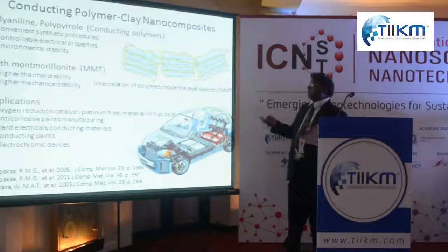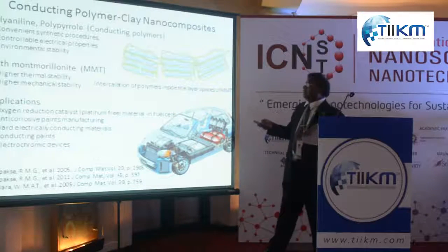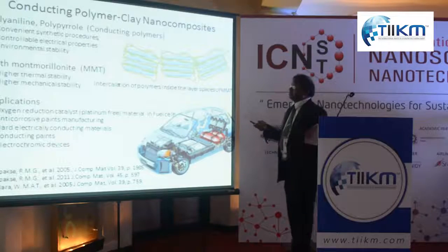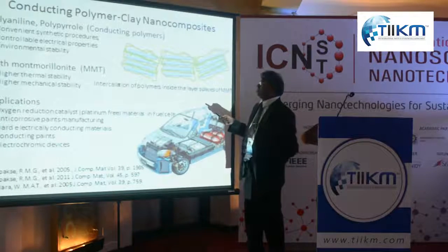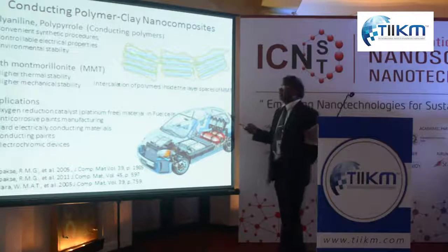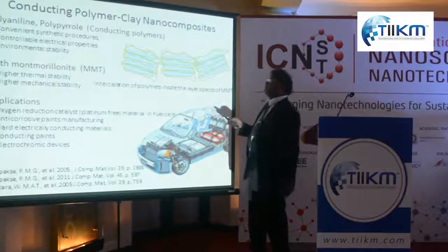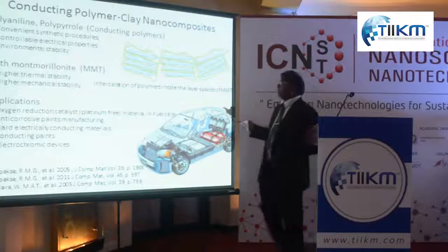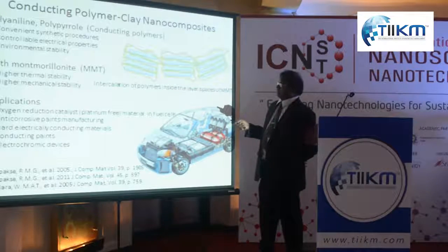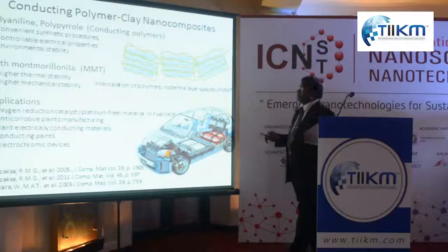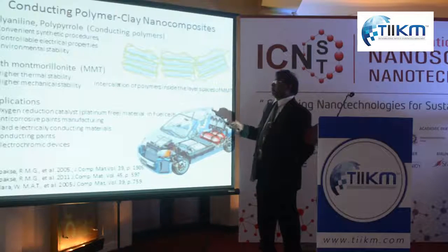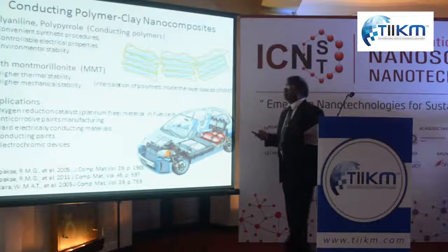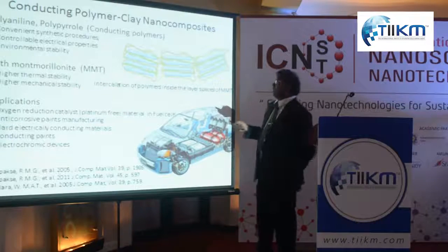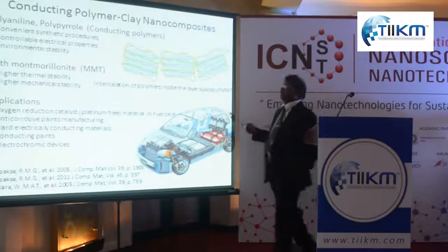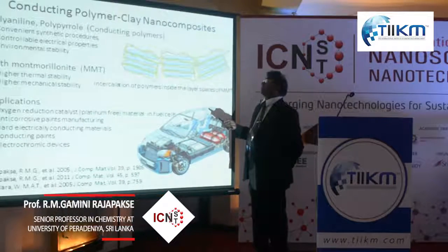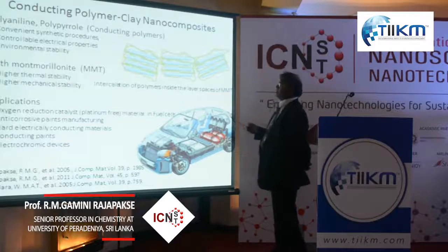And you can swell these clays because these interlayer spaces can expand. So you can exchange normal cations like sodium ions in sodium montmorillonite for oxidizable cations like iron 2, cerium 4, even silver plus, and different ions. And this is in an aqueous suspension. You can simply add your monomer, then the monomer molecules go in there, and in the confined environment electrode potentials are different. Even silver plus can oxidize aniline and pyrrole, you will see.